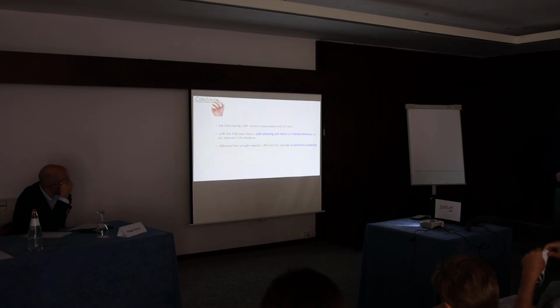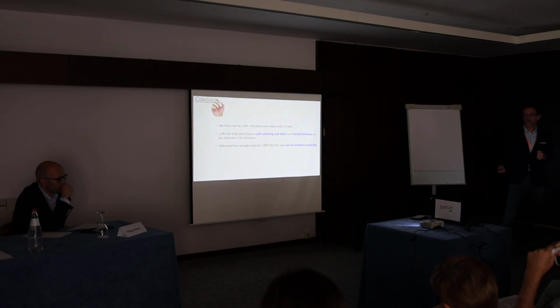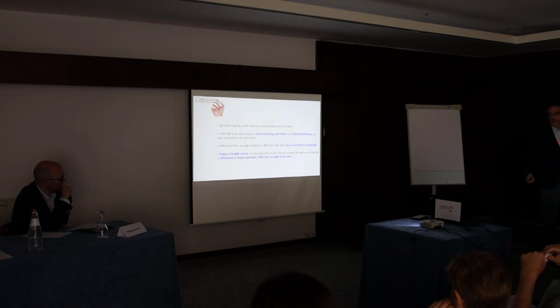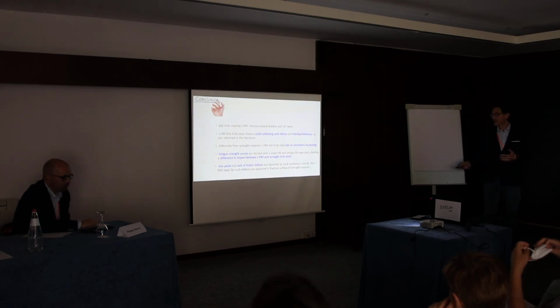Then I also showed you that, differently from the additive manufactured steel, the raw material exhibits a quite different behavior. In particular, it shows a secondary hardening not observed in the additive manufactured material. Finally, for what concerns fatigue strength curves, we tested two different approaches, Manson-Coffin and energy-based, and we found out from a statistical test that they have a statistically significant difference in the slopes. And finally, there is also a difference in the crack initiation sites, which are gas pores or internal defects for the additive manufactured material, while the crack nucleation sites are at the surface for the raw material.